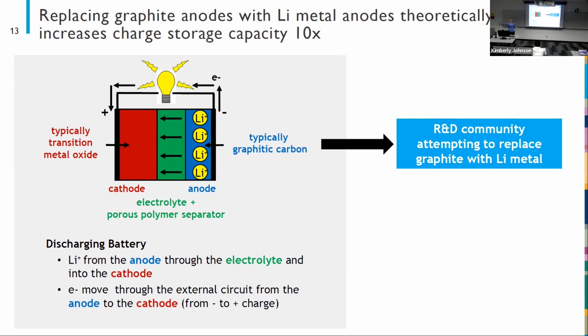Now, we all would like batteries to be smaller and weigh less for our devices. And so there's a constant push to get to higher energy density materials for batteries. One of the ways that we could do that is getting rid of these host structures that we're using. That graphitic carbon is basically wasted space and mass, because all we really need is to convert the lithium ion to an electron and lithium metal. If we could do that without a host structure, that would improve our energy density at the anode quite a bit.